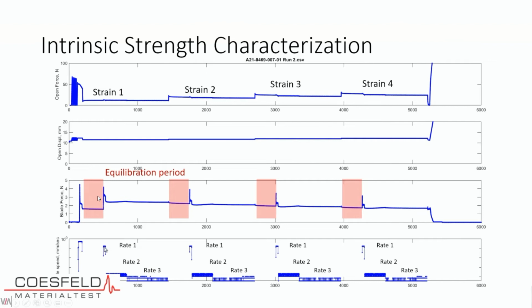So we start at the highest rate, and then we reduce the rate by a factor of about 100. And then we reduce the rate again by about a factor of 10. The idea being that, as you're cutting, again, we want to eliminate any viscoelastic effects in the material. And so by cutting at slower and slower rates, the viscoelastic effects get smaller and smaller. By measuring this over a few rates, we can observe that and verify that we've succeeded in eliminating those dissipative effects. So this is the basic schedule of things that happen during the test.